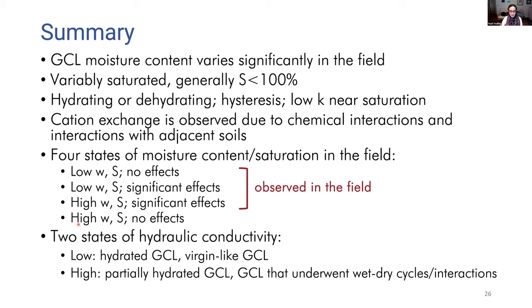And also the final possibility is high water content, high degree of saturation, no effects. This is a case where the material has just wetted and stopped there, didn't have any further interactions in terms of drying out, further cycles, and it's hydrated and it's perfectly fine in terms of hydraulic conductivity. During our exhumation in the field, our data is not fully published yet. We observed all of these three conditions, and this has been reported in some cases in the literature.